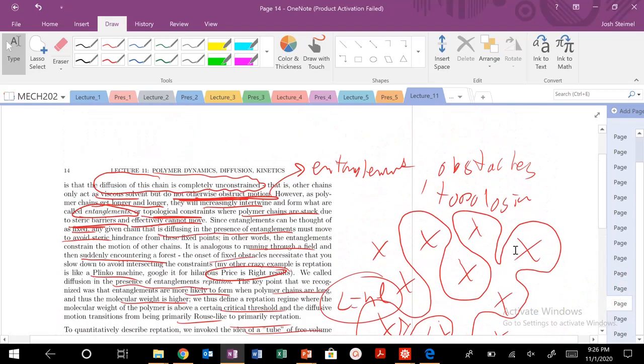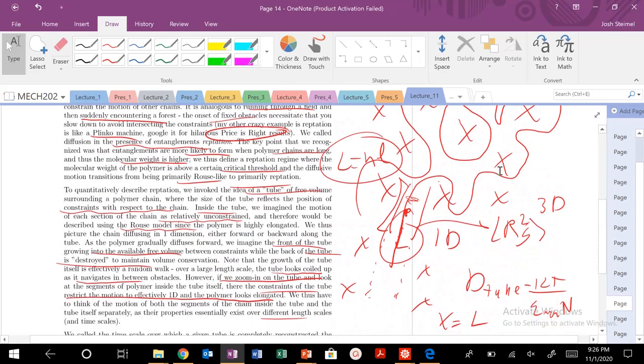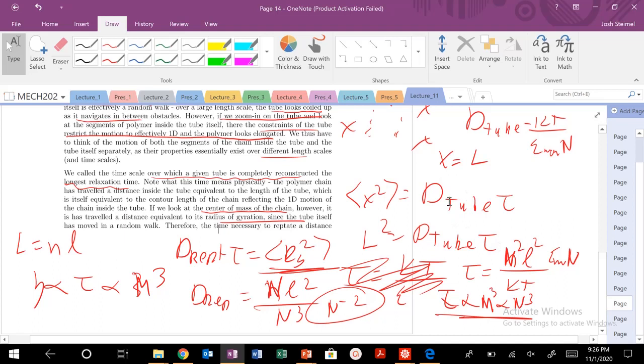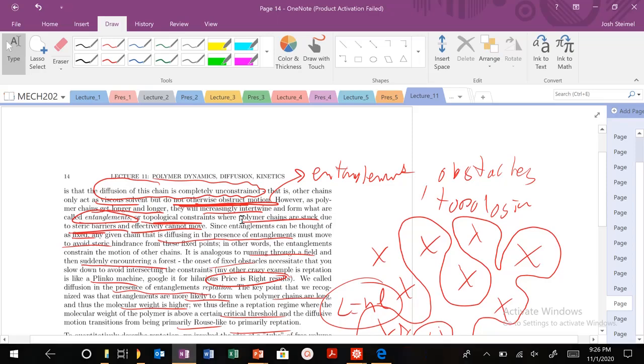When trying to describe the diffusion of a polydisperse melt, you want to use the weight-average molecular weight. It will better characterize the molecular weight of the large polymers in your sample — your rate-limiting species. If you have a large number of large polymers, it's going to move much, much slower. The key ideas here: reptation regime means high molecular weight, permanent fixed topological obstacles. Know how to do this derivation of relaxation time and diffusion, and how viscosity is going to scale. Reptation is a really unique derivation that de Gennes and Edwards figured out, recovering the scaling we observed experimentally.